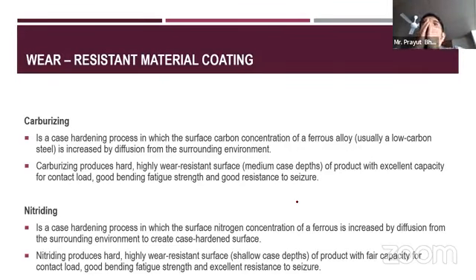This is not basically what I would say, adding a second layer, a completely composite material kind of thing, but it is adding a certain element only. It's changing the chemical composition that we were discussing previously. So this is the carburizing process, again very popularly used in a lot of industries. This is a process in which the surface carbon concentration of a ferrous alloy, normally a low carbon steel, is increased by diffusion from the surrounding environment.